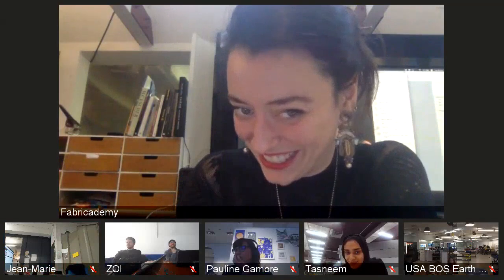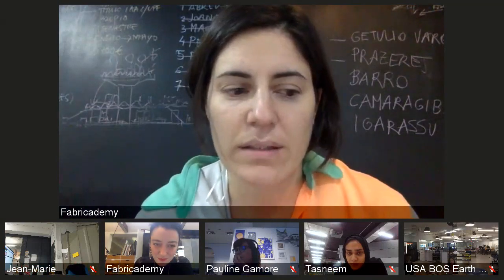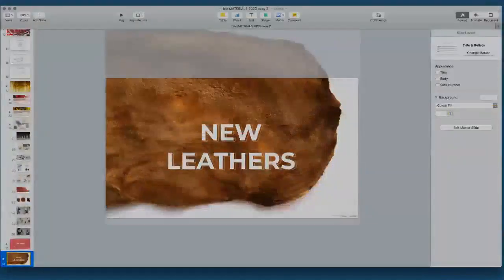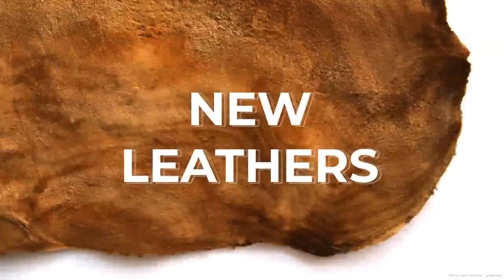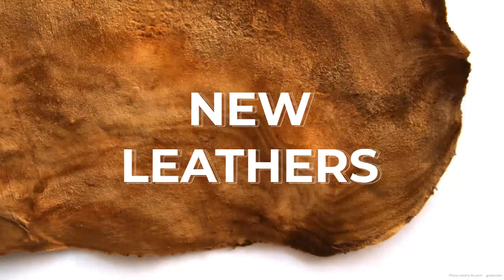It's already 5, and I'm not even halfway. I will continue. So one quick comment for Jean-Marie, because here we had issues with molding on the bioplastics, and the way that we fix that is that when we cast on the flat surface, we leave the surface drying at an angle, not horizontally, so the water excess will just drain out, if it's thin enough.